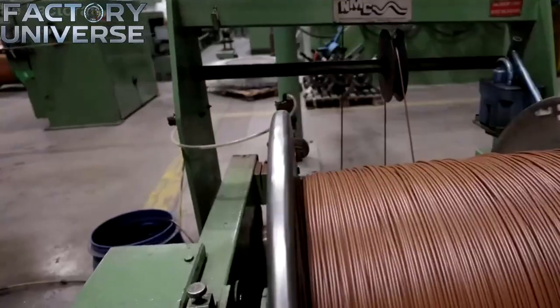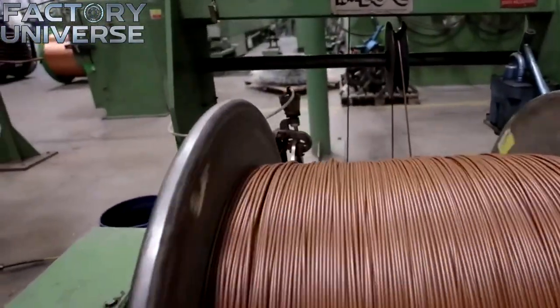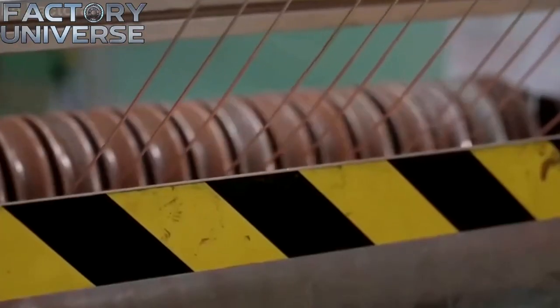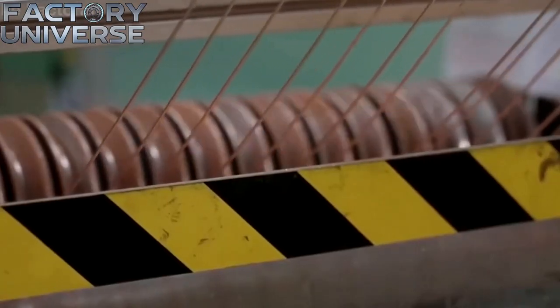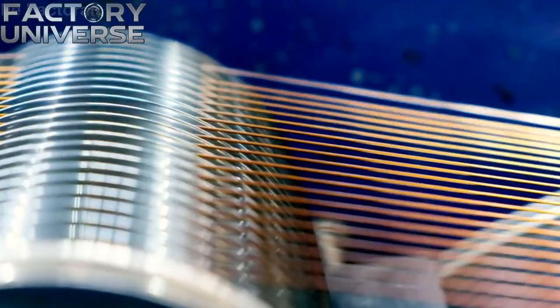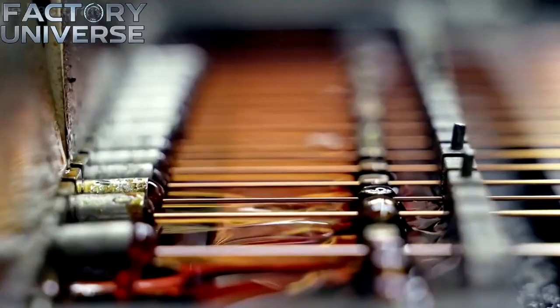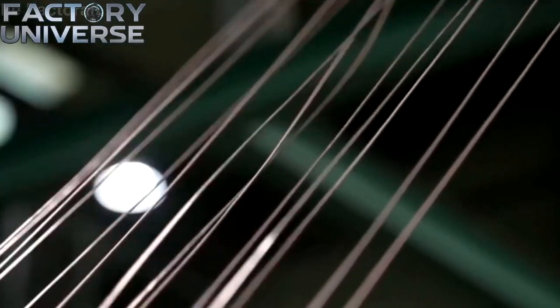Wire drawing does not happen in a single step. It consists of a sequence of gradual reductions where each adjustment is extremely small. It is visible how the metal gradually thins as a single wire typically passes through 10 to 30 different dies before reaching its final specified size. For example, from an initial diameter of approximately 0.5 inches, the wire can be drawn down to roughly 0.08 inches. It gets more complex further on.